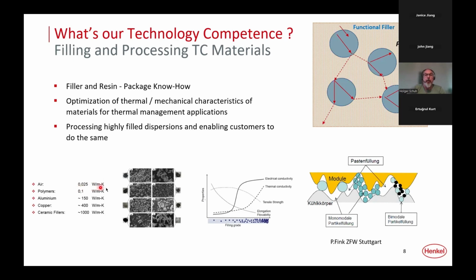But our competence is that we're using different types of polymer structures like silicones, polyurethanes, or epoxy, and using what we call functional fillers. That's mainly filler technology with ceramic nature. Depending on the type of filler and how we bring those fillers in at a certain filling rate and how we pack those fillers together into this resin matrix, we make the material thermal conductive. Classically, the more of those fillers you put into a silicone, for example, the higher the thermal conductivity will be.